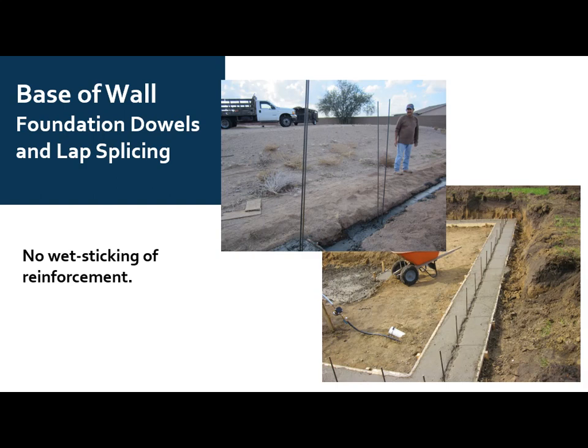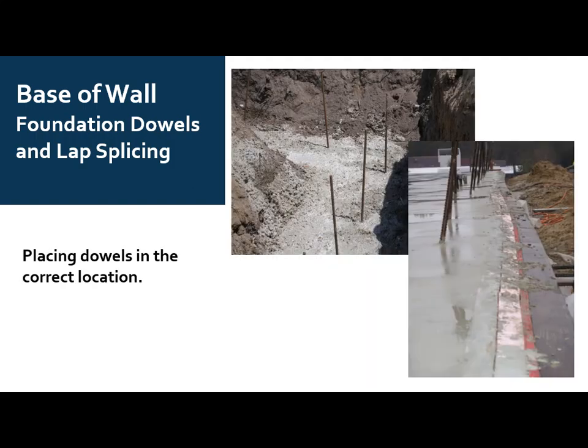But it's Arizona, it's fairly dry. I'm assuming they're probably not getting a whole lot of corrosion issues with that rebar that's actually buried in dirt, not in the concrete itself. But obviously not a good construction practice. We've got to maintain our cover distances around that footer steel, just like what we do with the exposed above grade wall as well. The bottom picture shows a little bit more of that wet sticking. So this was a situation where they came in after the fact, and all that little toothing that you end up seeing there, that's where they came in and placed the hook on the bar into the footer itself.